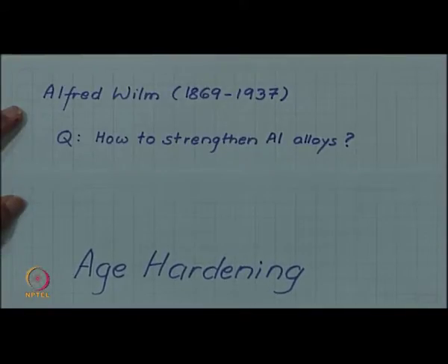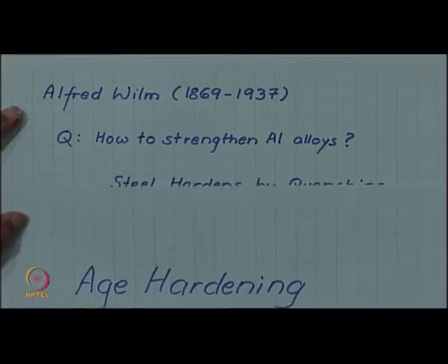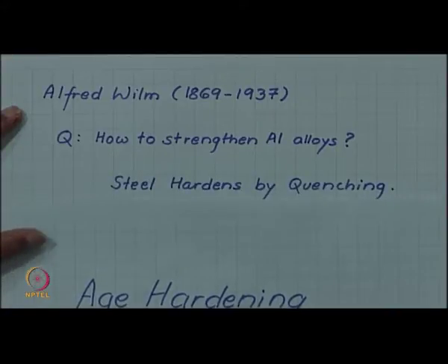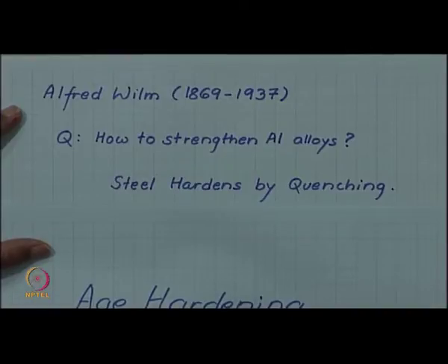So then he had the background from steel, that steel hardens by quenching. So we have seen that steel, if taken to the austenite phase field and then quenched rapidly enough to miss the nose of the TTT curve, it hardens because it forms a very hard and brittle martensite. So steel hardens by quenching.